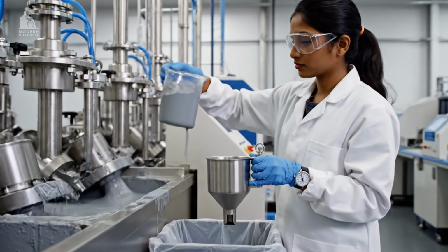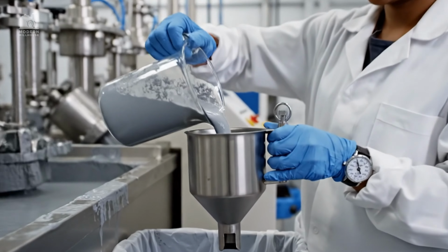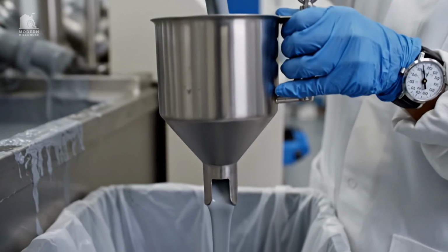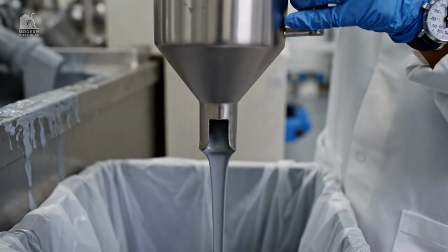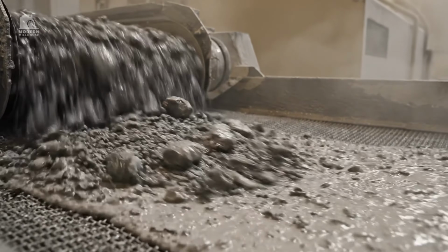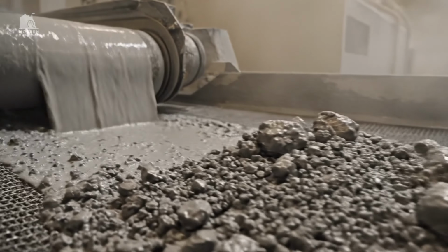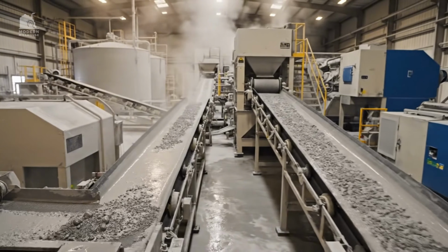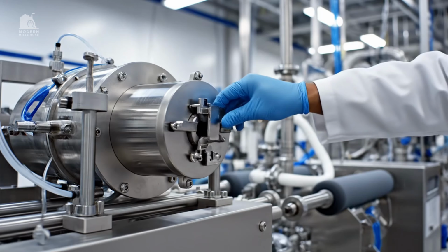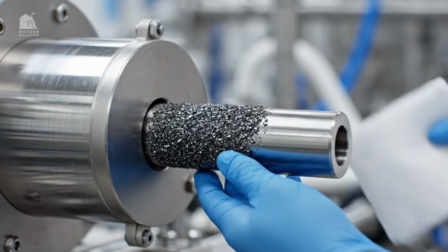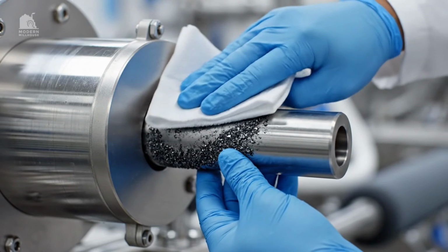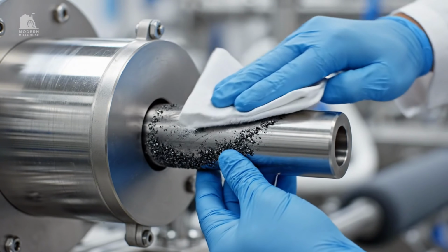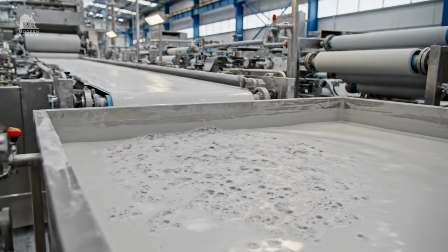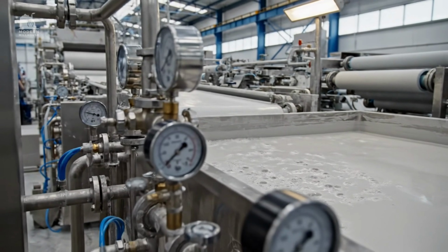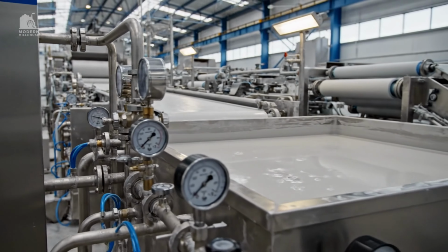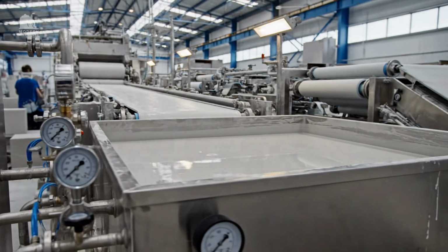Chemistry matters too. Deflocculants keep particles dispersed so the slurry stays fluid with less water. Less water means less energy later, because the spray dryer has less to evaporate. Anti-foam agents prevent trapped air that could later cause bubbles in granules and glaze defects. Some plants de-air the slip in vacuum tanks so pumping is smoother and spray drying is more consistent.